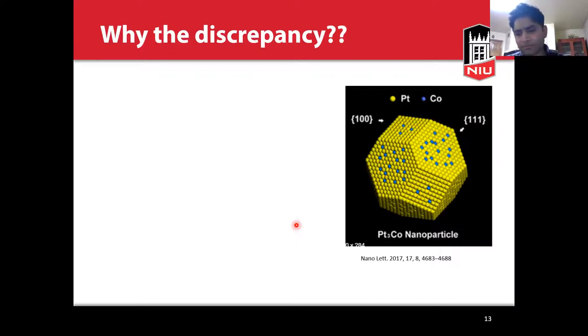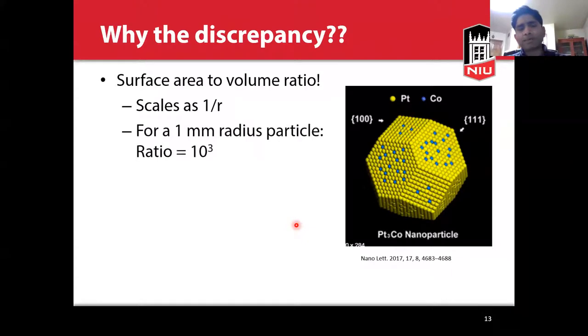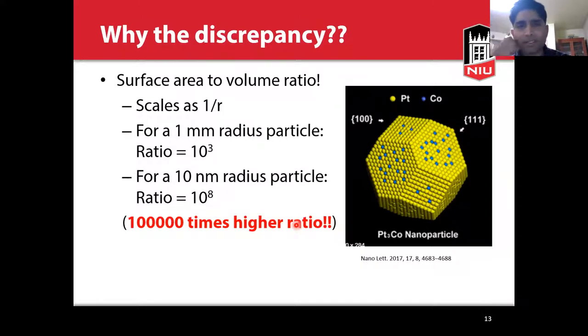So let's take a simple calculation here, okay? What really happens is, let's take a sphere and look at the surface area to volume ratio. The surface area of a sphere, going back to your high school, middle school, would be 4 pi r squared. The volume of a sphere is 4/3 pi r cubed. So if I take the ratio of that, that ratio scales as 1/r, where r is the radius of the particle, right? Now, if I take the ratio for a 1 millimeter radius particle, the ratio comes out to be 10 cubed, or 1,000, right?